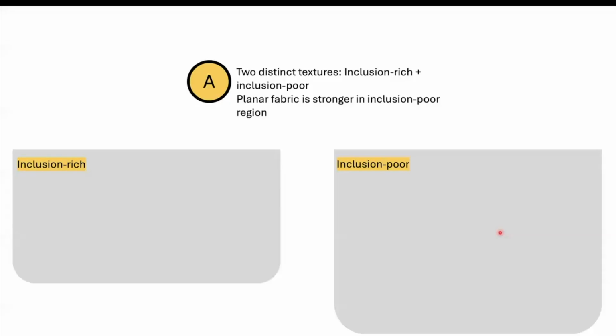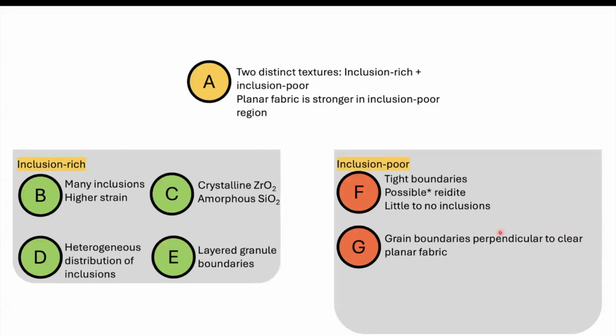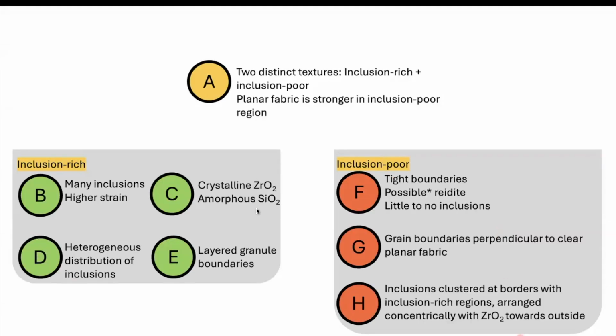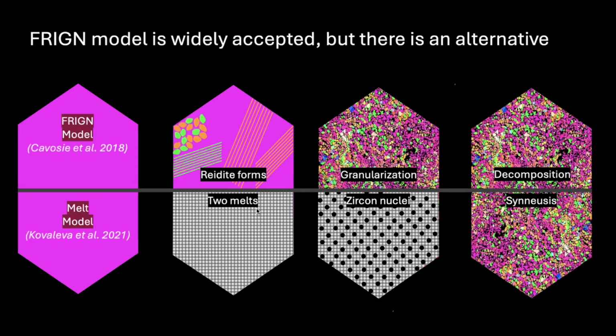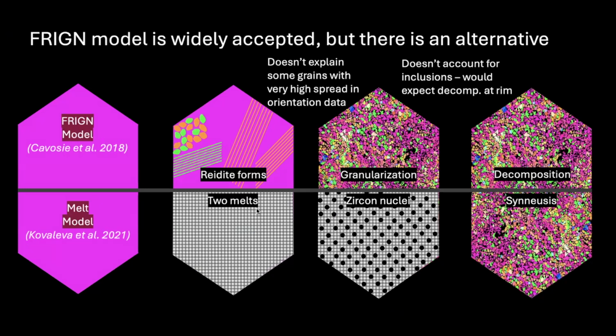So what created these textures? We have two distinct textures. Here's all those pieces of evidence that we just gathered, and let's go through these models. Unfortunately, the FRIGN model doesn't explain some grains that have very high spread in orientation data. About 10 degrees of spread makes sense, but some of them have way more than that, including one of the ones I showed. It doesn't account for inclusions inside. We would expect there to be decomposition at the rims of a grain, maybe even the rims of granules, but not interior. But then for Lisa Kovaleva's model, how would you get a planar fabric in this situation?